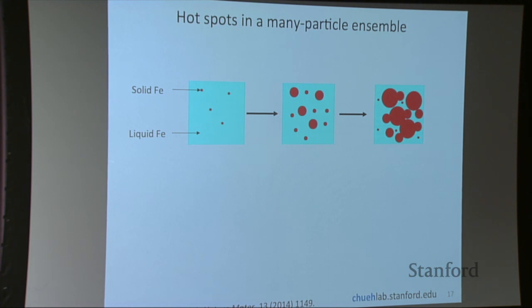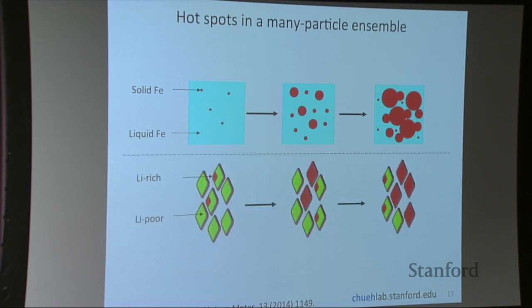But in a battery system, this can't happen because the batteries consist of individual particles isolated from one another. So you have these phenomena occurring in each individual particle. They're getting activated. But once the activation propagates to fill the entire particle, it stops. Okay? So when this particle is full, you need another event for another particle to start nucleating. So the rate of this nucleation actually determines how many of the particles are active.